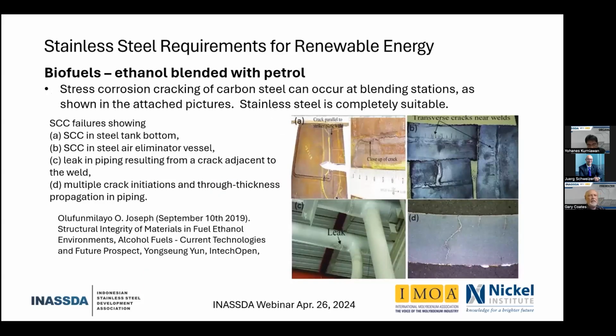Now, when you take this bioethanol and blend it with petrol or gasoline, as we call it in North America, you can get stress corrosion cracking of carbon steel. Of course, petrol, gasoline, you can normally handle with plain carbon steel, but when you blend it with ethanol, that water, chlorides, and acid in there can cause stress corrosion cracking of the carbon steels. There have been a number of cases at the blending stations, where they mix the ethanol with the petrol, where you have experienced that. And of course, you don't want to have leaks of a very flammable fuel there. So those tanks and piping systems are most often stainless steel, again, 304L or 316L.